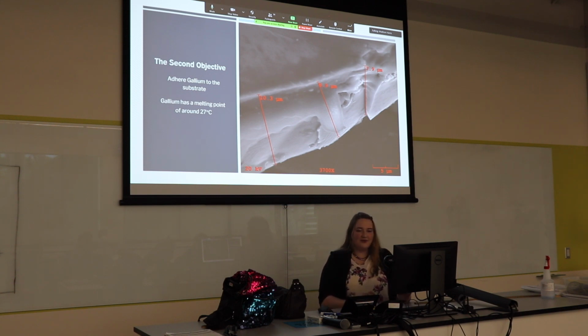The problem with this is that the gallium, because it was so warm and easy to put on, smoothed itself out and ruined the nice texturing process that we did in the step before, which we didn't think about ahead of time, but it's all right. We still just wanted to be able to get the gallium onto the silicon and see if we could grow a film on top of gallium.